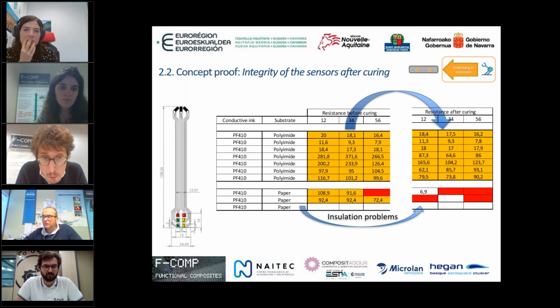With other substrates, for example with the paper, the issue was related a little bit with the CTEs of the different materials. The different deformations between the layers, the carbon against the paper, make the ink crack, because the difference in the deformation generates stresses inside, and the tracks are broken. So what we have, you can see in the bottom line, is an insulation problem. We started having some resistance in the track, and finally we have zero. So it does not work. This is why, even if the papers were the most promising solution in terms of mechanical properties, in terms of functional, we have to discard them.